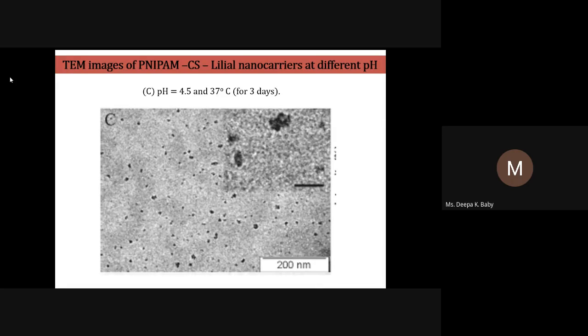And this is the TEM image of the same micelle at pH 4.5 at 37 degrees Celsius. You can see the diminution of size to a large extent. That is, when it is taken to pH 4.5 and at temperature 37, the size gets diminished to a greater extent. So this is the point where we can use it as a drug carrier.